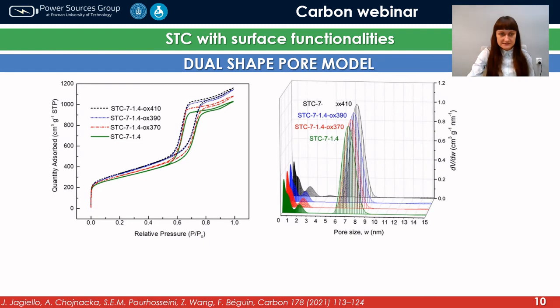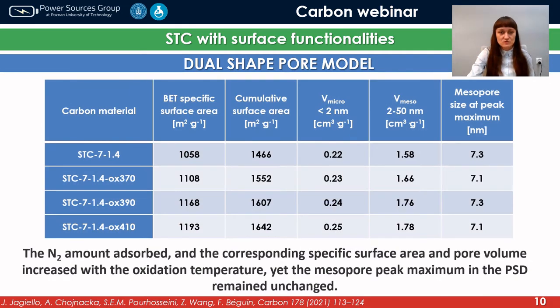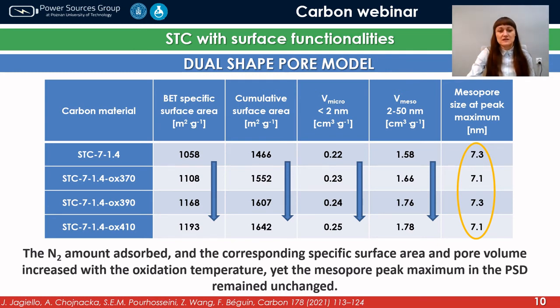So we applied the dual shape pore model also to samples with surface functionalities. In this case, we took one of the samples which I showed you before and oxidized it at temperatures of 370, 390 and 410 degrees Celsius. As you can see, the adsorption characteristics indicate that the oxidation process didn't damage the integrity of the pristine sample. However, some systematic changes occurred, and they are visible in the calculated data. Here, as in the previous case, we are using the same silica template, so the mesopore size is the same. However, all of the texture parameters are increased with the increasing oxidation temperature.